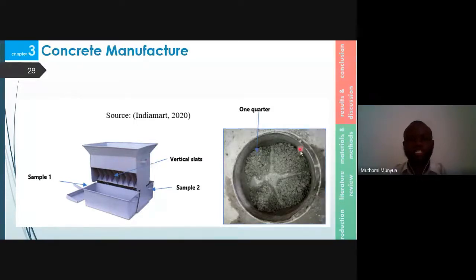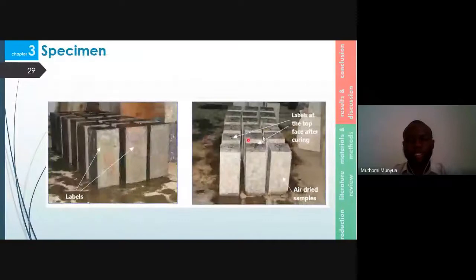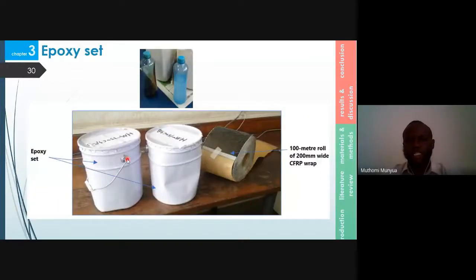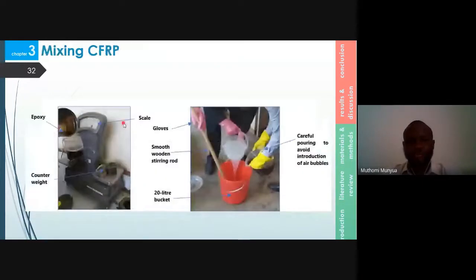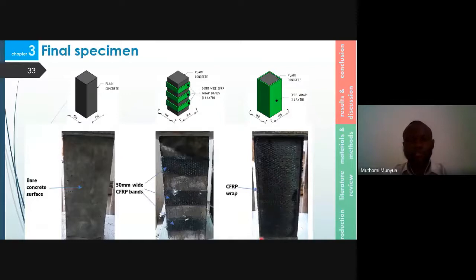These are the specimens after curing. These are the specimens just before application of CFRP. This was the epoxy set and the 100-meter roll of CFRP. Carbon fiber was cut to size using an ordinary pair of scissors and mixed according to the manufacturer's specifications. These were the final specimens, a slight difference from what was conceptualized, but very similar.